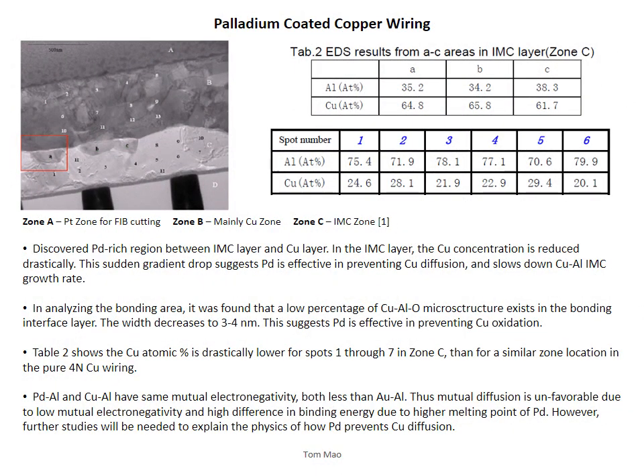Now for palladium coated copper wiring, they were able to show that palladium itself does not diffuse throughout, and also that palladium is effective in preventing oxidation and copper diffusion. They try to explain this by saying that palladium aluminum and copper aluminum have the same mutual electronegativity, both less than gold aluminum, and so this mutual diffusion is unfavorable due to the low electronegativity and the high difference in binding energy due to the higher melting point of palladium. But they don't go in depth into the physics of how palladium prevents copper diffusion.